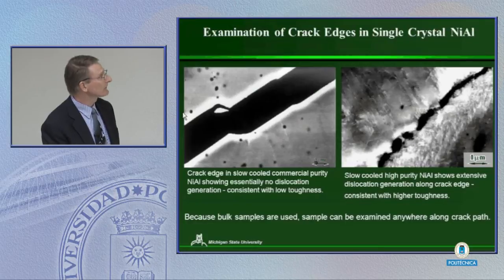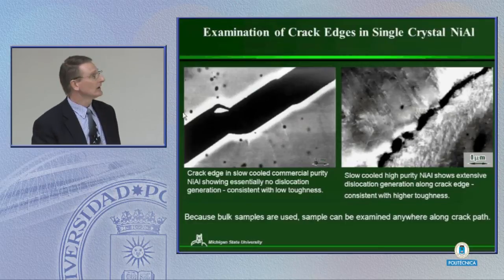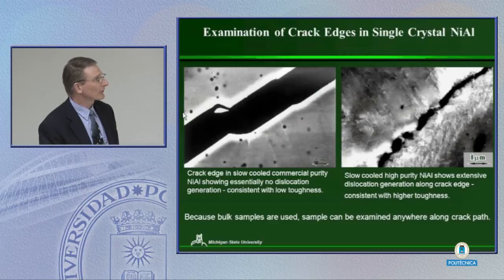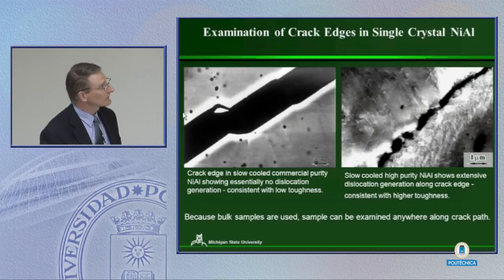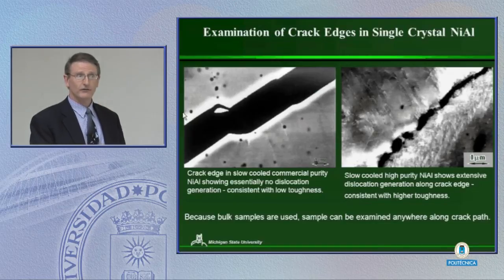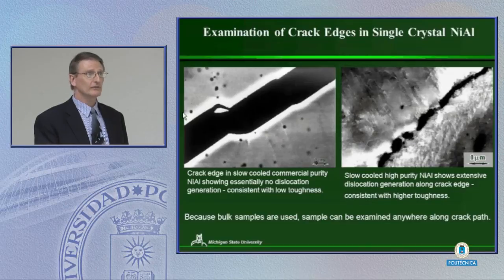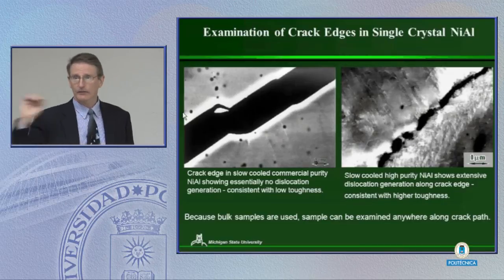And you can see that really it's a very flat fracture. In the same high purity material, slow-cooled, we can see it's a much more tortuous path. I think there's an indication of little bits of plasticity right along there. But we can also see dislocation slip bands along here. And we can see that those on this side go out to about here, which gives us a feel for how big that plastic zone was as the crack was dynamically propagating.